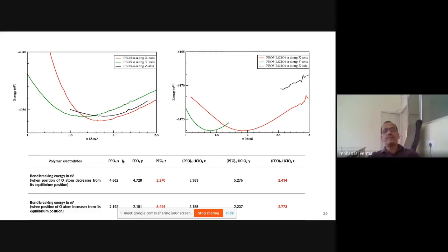I just take the coordinate part, not the lattice vector part. I just take the coordinate of that oxygen and shift it, with the x component shifted up to a particular level, from positive 5% to negative 5%, and likewise along the y-axis and z-axis, and the corresponding energy is calculated.